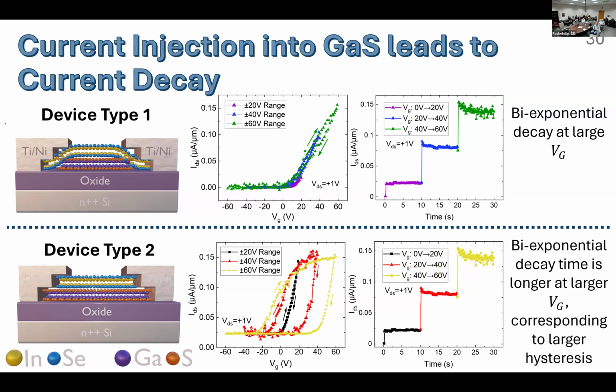So these traps will be activated once current is flowing through here, right? This shift in the threshold voltage occurs because the material underneath thinks that it's looking at a different voltage than it is. So for example, here you would expect this to be on at 40 volts, but instead it turns on around minus 20 volts. This is because there are traps inside the gallium sulfide layer that are making the surface around here appear more positive than it actually is. So instead of it actually being minus 20 volts, the indium selenide thinks that it is in a landscape where it's actually 40 volts. And so that's why you see this shift in the hysteresis.